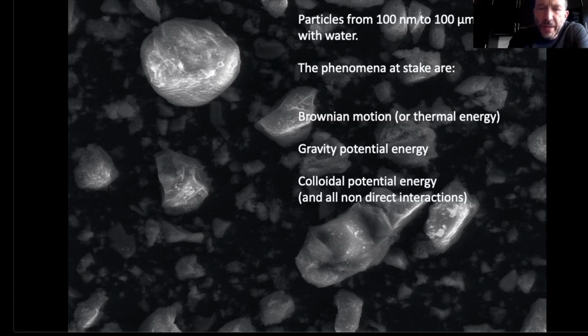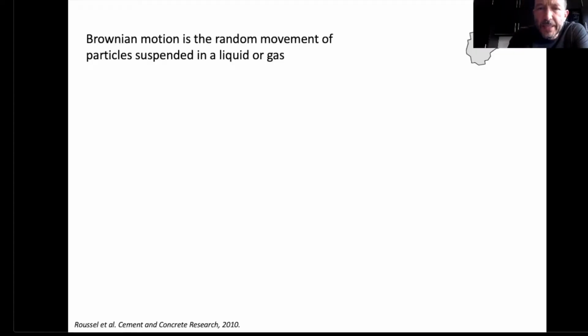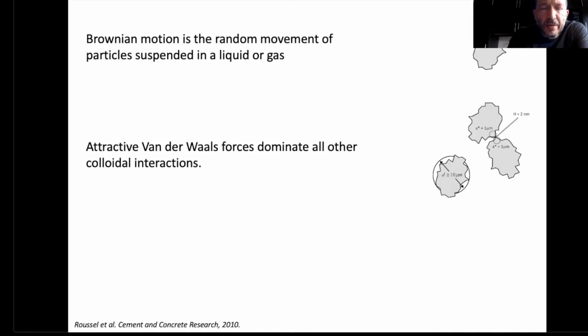Well, in the case of cement, all these phenomena are studied in detail. So we often choose to consider Brownian motion or thermal agitation as a reference, because it's something that can be easily assessed. And we have some colloidal interactions as well. They were shown to be mostly attractive van der Waals forces. And in fact, they do not depend much on the diameter of the particle. They are more concerned with the diameter, or the equivalent size, of the asperities on the surface of the cement grains.